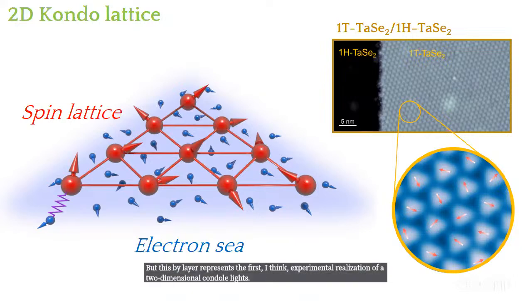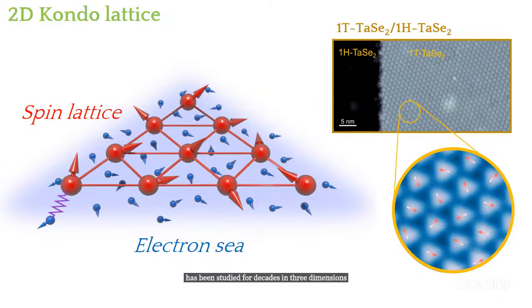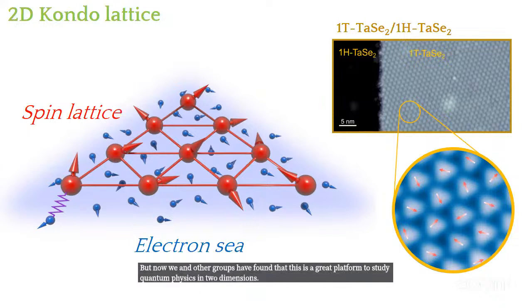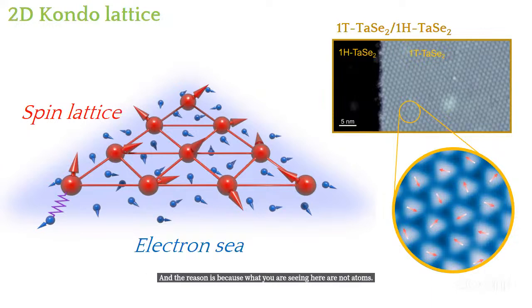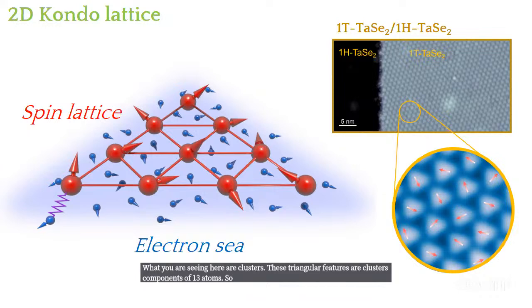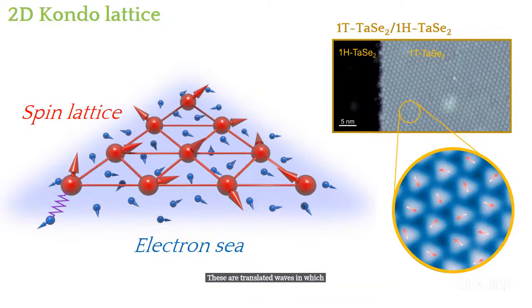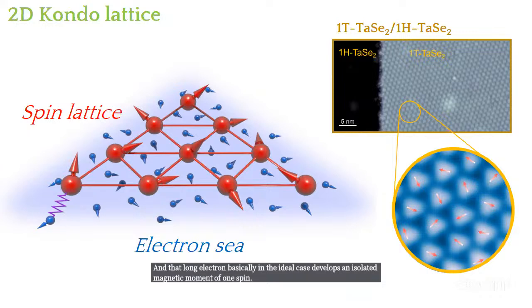The Kondo lattice has been studied for decades in three-dimensional materials, very complex materials with very crazy stoichiometries. But now we and other groups have found that this is a great platform to study Kondo physics in two dimensions. And the reason is because what you are seeing here are not atoms. What you are seeing here are clusters. These triangular features are clusters composed of 13 atoms, okay? So this is a charge density wave in which, due to the band structure, there is a lone electron confined within each of these triangular features. And that lone electron, in the ideal case, develops an isolated magnetic moment of spin 1/2, okay?